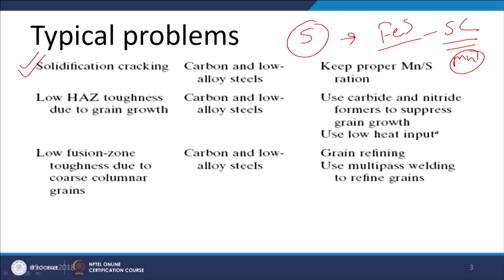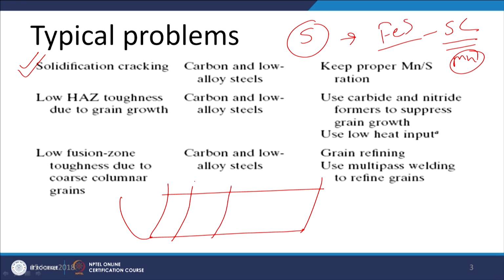As I have explained, the heat affected zone and the weld metal of transformation hardening metals like steels lead to the formation of coarse grained martensite, which leads to a reduction in toughness and increased embrittlement of the heat affected zone. So, sometimes we require post weld heat treatment to restore the toughness, or controlled alloying also helps to reduce embrittlement or control the loss of toughness of the heat affected zone and of the weld joints.